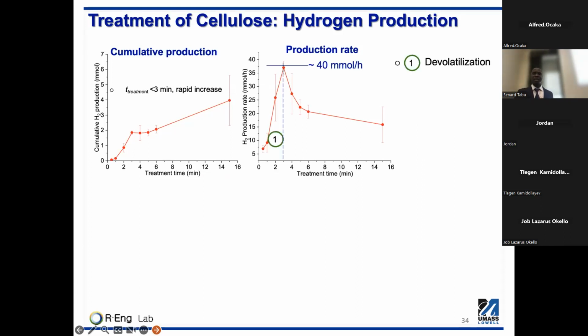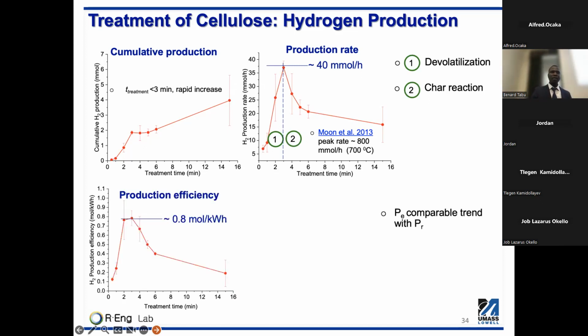According to different authors, the treatment of cellulose occurs in two different regimes. There's a devolatilization, which results in the production of more volatile compounds, and then there's a char reaction, which results in more charring. We see that in the first regime, devolatilization dominates over the char reaction. According to Moon et al., when you have the synergistic effect of devolatilization and char reaction, that's when you have the maximum production. The hydrogen production efficiency follows more or less the same trend as the hydrogen production rate.